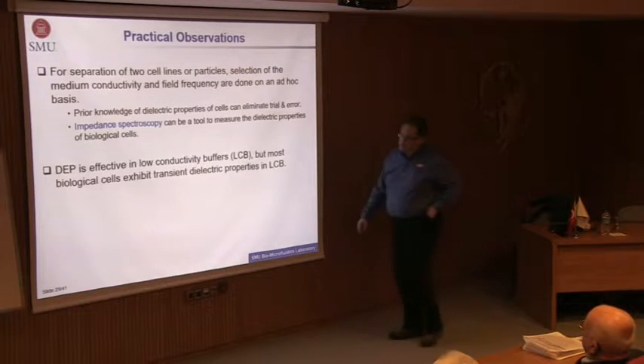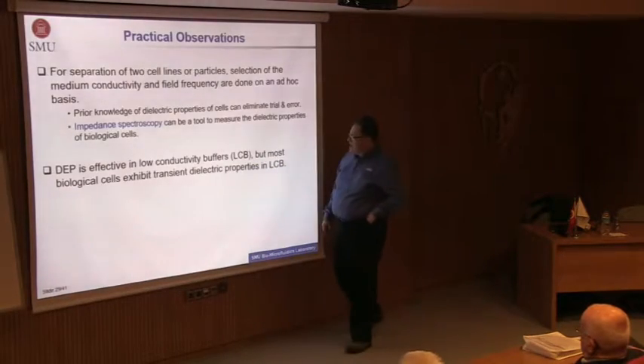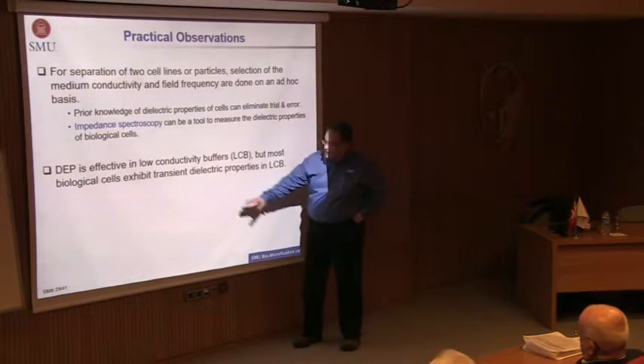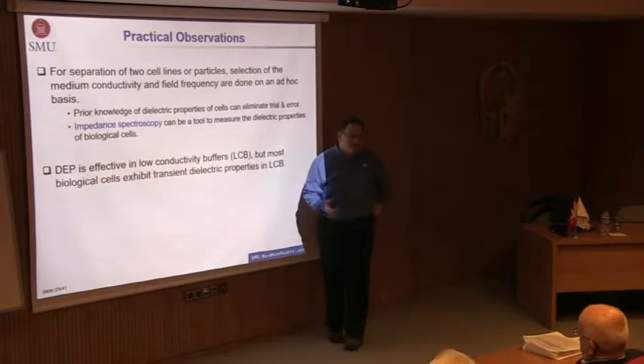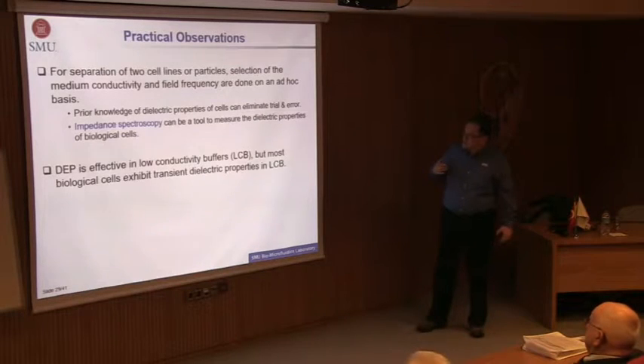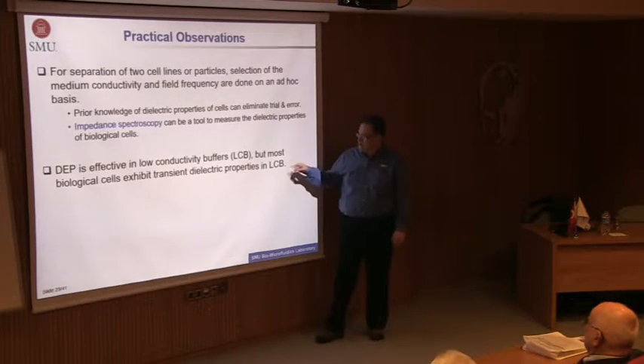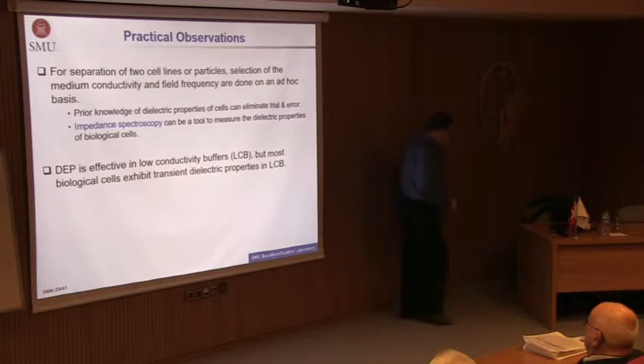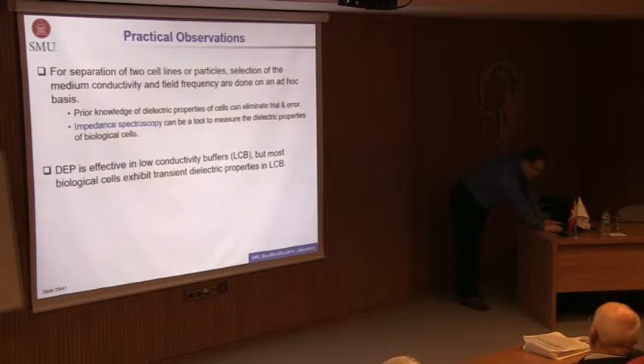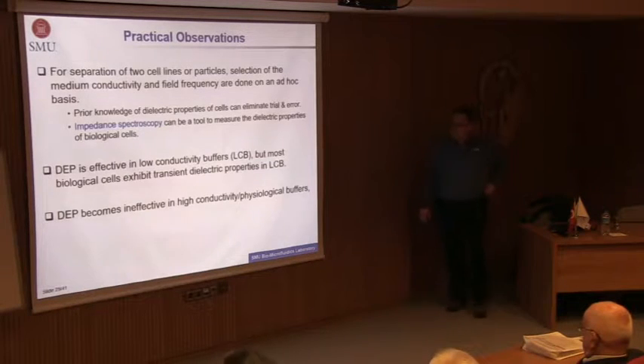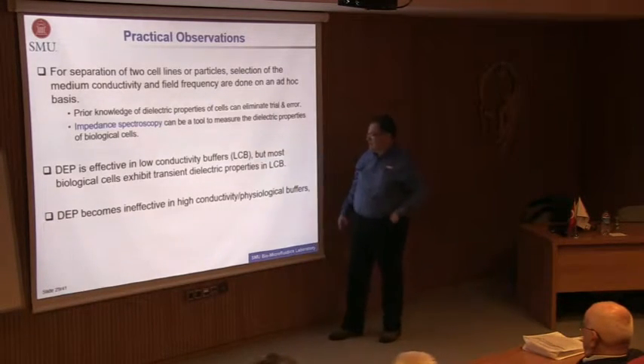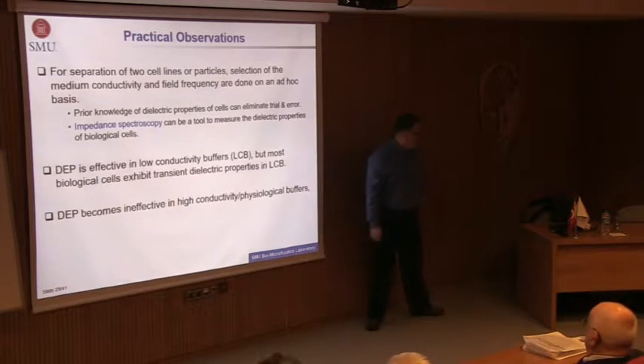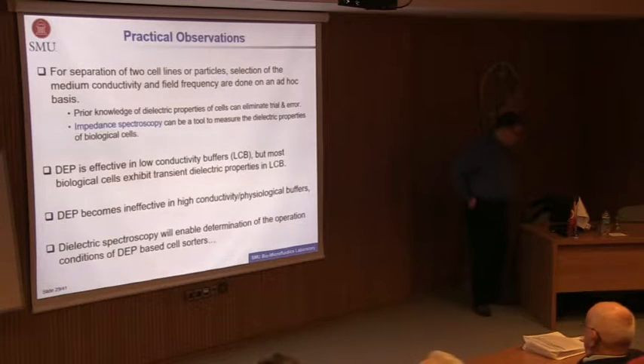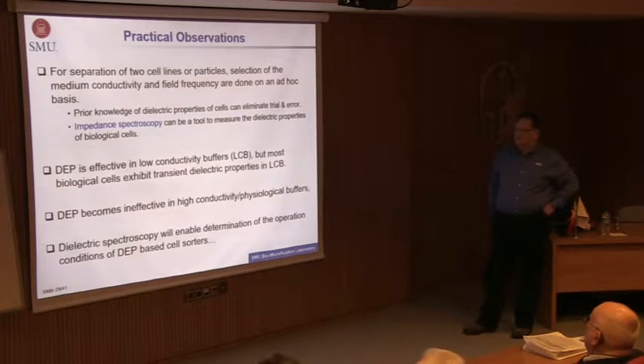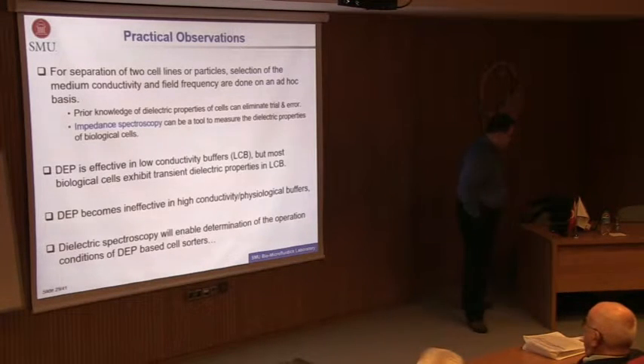And another observation is DEP is effective only in low conductivity buffers, and most biological cells exhibit transient dielectric properties in LCBs. Just like, you know, the biological cells would like to pump ions out in order to equilibrate with their environments. So making experiments in transience is not a good idea as well, and that was not very well described in the literature. And another observation is DEP becomes ineffective in high conductivity medium, especially in PBS solution and plasma and so on. So we basically try to address these needs so that we can create something useful.